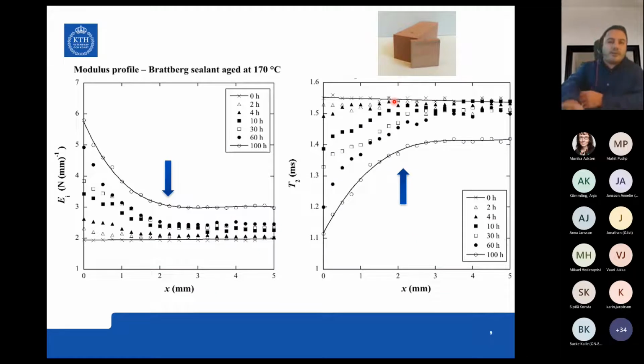So these are again from my old thesis, just to show you guys how we did some profiling with the NMR. So the image to the left is an indenter modulus profile. So this is the surface hardness, and this is the distance from the surface. So the surface is essentially here, and this is 5 millimeters in, and this is the image of the block that we have screened. So as you can see from this surface hardness, you see that because of the high temperature aging, we have a lot more oxidation at the surface compared to the bulk. And if we look at the NMR, we see the same pattern, but it's flipped. So we see that at the surface, we have far less relaxation times. So the relaxation times are shorter.